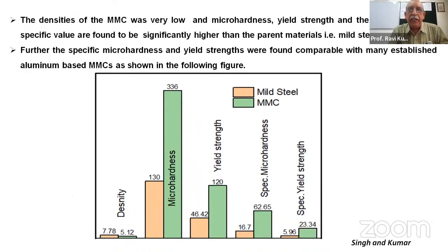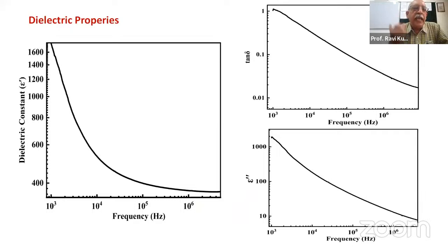So finally, these materials we found, and we believe that they have a core shell type of structure, which we already studied. If you have a core shell type of material, it will show dielectric properties. If one looks at these data, we measured the dielectric constant as a function of frequency. It has a very nice dispersion relation, and at around 1 kilohertz, the dielectric constant is around 1600 or so, which is a very large dielectric constant.